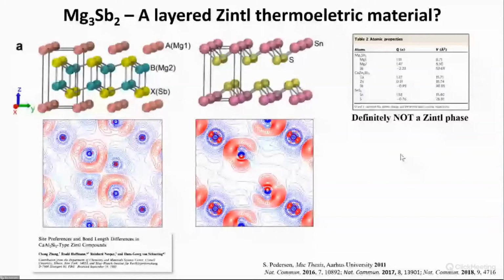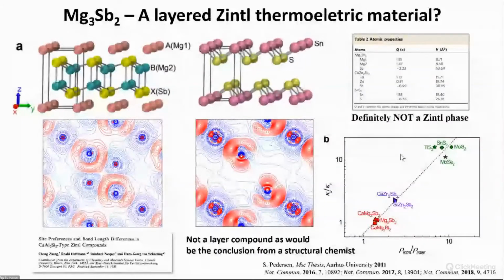And of course, the conclusion here is that if you were a structural chemist just looking at the positions, you would not really get the true view of it. One thing that really nailed it was that if we look at the thermal conductivity, or the anisotropy of the thermal conductivity, then it's almost an isotropic compound.